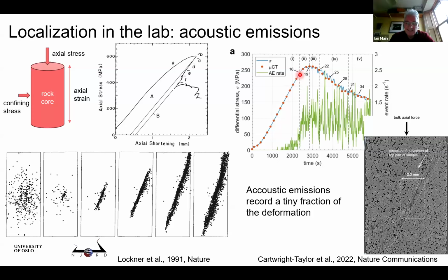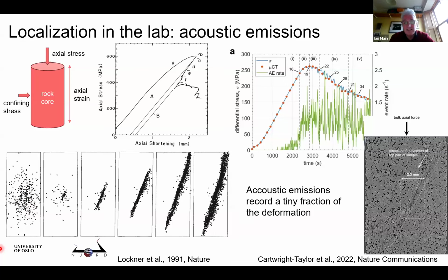some localization starts. Yeah. It's a mixture of sort of hardening and softening processes, I think. Yeah. What looks like linear elastic is linear, but it's not elastic. You do have damage, you've got compensating cracks closing and opening, and somehow that averages out, or I don't know how to express it more scientifically, but it's certainly not elastic. It's not going to be recoverable, if you take the stress off, you're still going to have the damage. And you see that in the acoustic emission, you start some activity here. Exactly. It's still in the elastic part. It's just that the strain is small. So you've got these two maybe competing processes, and you add them up, and they produce the apparent linear response in the rheology.